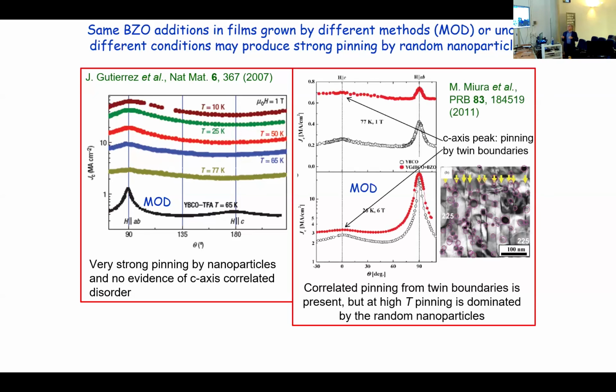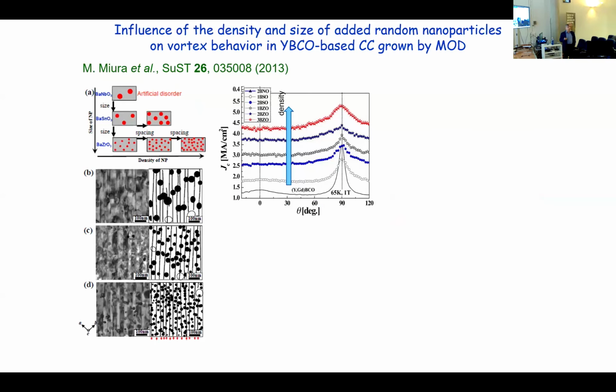We did similar work, led by Masashi Miura when he was our postdoc at Los Alamos, and we also introduced nanoparticles in MOD. We show huge improvements at high temperatures, only modest improvements at low temperatures with the particles, and that was due to the fact that the nanoparticles were very large. We made systematic studies changing the chemistry and the density of the nanoparticles, and I will not talk about that because you have done everything about that at this point.